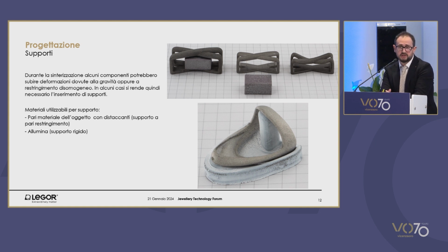In the green one, the powder supports the object while it is growing, so there is no mechanical issue here. But when I'm sintering the item, unless I use a support, of course you can place the brick also in a different way, but here it acts like a bridge. The bridge that you see in the item on the right indicates the distortion caused by gravity. So the solution could be placing this brick and considering the tolerance of the object after sintering, so that the object can be supported rather than caving in, and giving me the possibility to extract the brick after sintering.